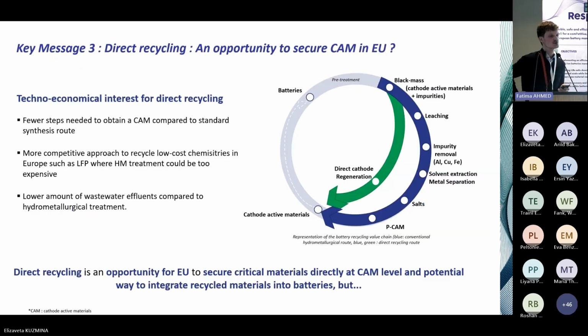Just one slide to reintroduce the concept of direct recycling. So the idea is to say that in black mass, we have a lot of intact cathode active materials. Can we find a way to directly reuse these cathode active materials contained in this black mass and avoid all the process steps of the hydrometallurgical treatment? From a theoretical and utopical point of view, if we manage to do so, we could have less process steps than in the hydrometallurgical treatment.